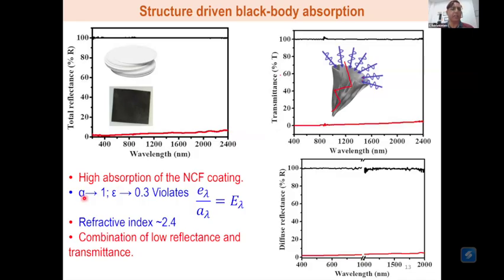And that is what gives us an alpha, the absorptivity, which is very close to 1, whereas the emissivity, because of this cavity geometry, is around 0.3 to 0.4, which is actually violating Kirchhoff's law of thermal radiation. And you know that these kinds of violations are very well known in the literature, because cavities are one of the best absorbers and one of the poorest emitters.